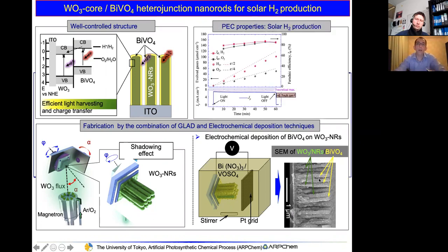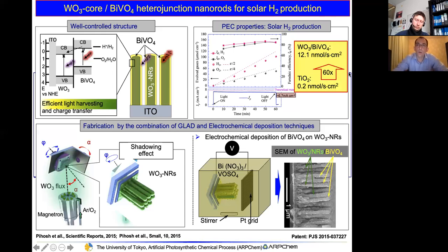Okay, and about the solar hydrogen production. This is the result from the gas chromatography on the detection of hydrogen and oxygen during the evolution. If we compare with titanium dioxide, the rate of evolved gases on this material, we realized about 60 times enhancement for the production of hydrogen. So it's really a big number.